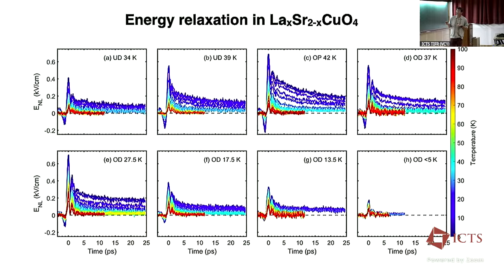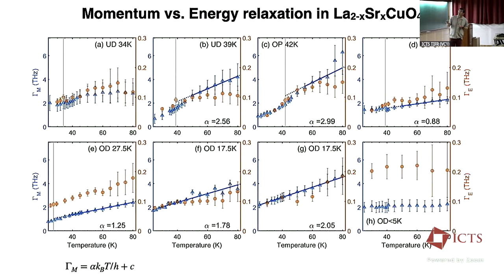We've worked on a lot of samples which span the underdoped all the way up to the overdoped. These are plots where we pump the sample with a terahertz pulse and then come in at some later time and probe the sample and look at the response. Red is warm and blue is cold, and these curves can be fit. On the next page, on the left side is the momentum relaxation rate, literally just the width of this Drude peak that we get from linear response. In red, I'm plotting this other response, the energy relaxation rate. They're plotted on different scales. Note the different scale between the two sides here. It's approximately a factor of 20 between the left and the right sides.